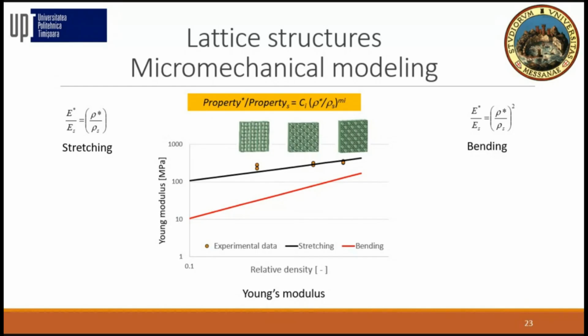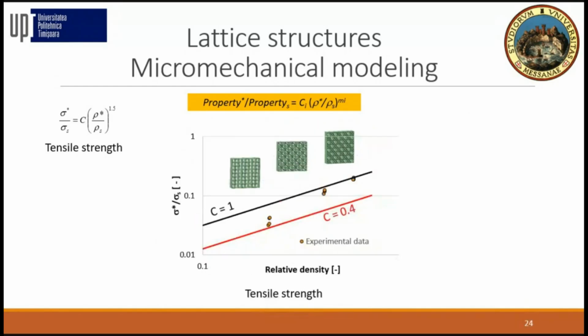Then we use the same model for stretching to predict the tensile strength. The tensile strength is between these coefficients, 0.4 to 1, multiplied by relative density to the power 1.5. So we only check against this. We didn't try to come up with another micromechanical model from here.